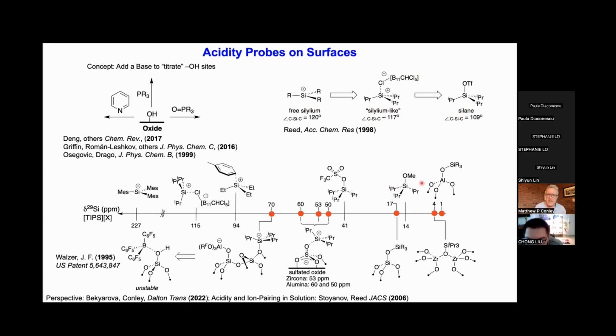So when you have silanes, you have shielded NMR chemical shifts. When you have a pure silylium, you have a very deshielded NMR chemical shift. And then you have everything in between along the spectrum between silane to the free silylium, where as you become more silylium-like, you gradually deshield the silicon NMR chemical shift.